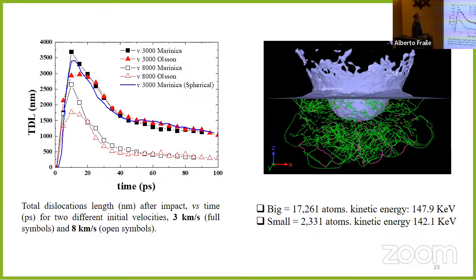We could analyze a lot of things. One of the important things is that it is size dependent. What I'm showing here is two curves. Total dislocation length goes up and then down. As I said, we have recombination. In this case, these full symbols are 3 kilometers per second, and these empty symbols are 8 kilometers per second. So velocity is different, but because the size of the projectile is different, the kinetic energy is the same. So being the kinetic energy the same, we have different results. It's because it is size dependent. So this will be clear now.